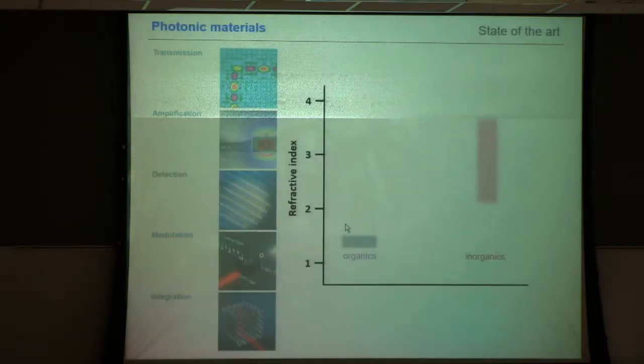So what can we do? Why people haven't used organics yet, except for light fibers, is that organics have one big issue. They're made up of carbon and hydrogen, if you're lucky some nitrogen, and if you go to the conducting material, sulfur or so. But therefore, the refractive index is really small. And it's not necessarily the value that counts when you do photonic devices, but the contrast. But you see, you're very limited in getting large refractive index contrast with organics.